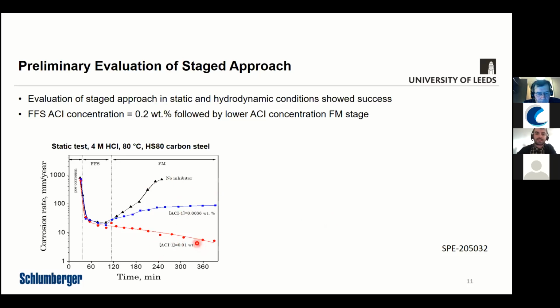But the key thing here is that the film maintenance stage concentration was significantly lower than the concentration in the film forming stage, which was 0.2 wt.%. So considerable difference in the inhibitor concentration that was used in those different stages. So quite a dramatic reduction in the corrosion inhibitor concentration used.